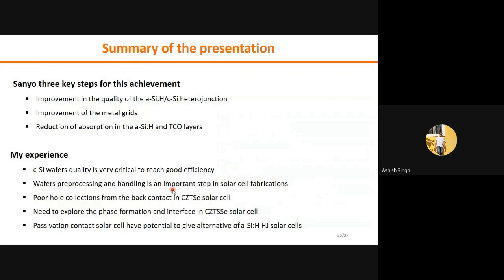Now we are moving to the summary of my presentation. From the first section we can summarize that Sanyo gave three key steps for achieving a good efficiency solar cell. If we want to work on the amorphous silicon based heterojunction solar cell, we need to assure the amorphous silicon quality and how it makes the junction with the crystalline silicon. The metal grid is also critical. Shadow loss should be minimum, and the silver paste should not spread throughout the sample. In addition, we need to work on reducing absorption in the amorphous silicon and transparent conductor layers.